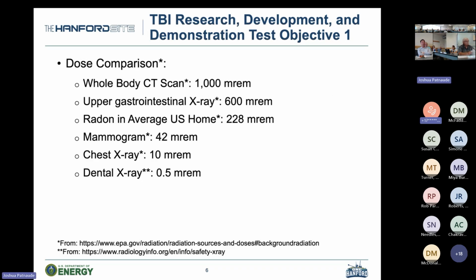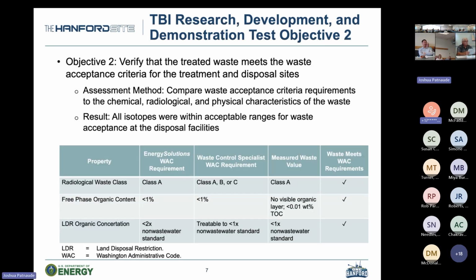Next slide, kind of put that into context. A radiological dose, that's about what you would get from a dental x-ray from your annual visit to the dentist's office. Next slide. Objective 2 had to do with meeting the waste acceptance criteria for the disposal locations in Utah and Texas. And so based on the criteria that those sites had for their radiological waste classes, free phase with the organic contents and the LDR organic concentration, our sample results demonstrated that we met all of those criteria for the shipment and transport to those disposal locations.